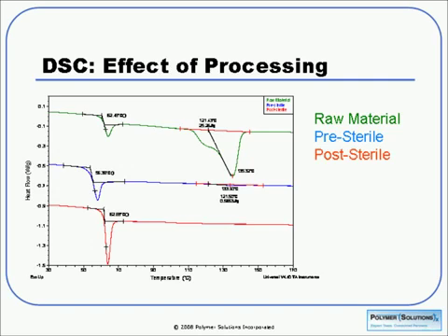We also see an endothermic peak overlaid on our glass transition, and this is related to physical aging. We've mentioned free volume of our samples. Well, if you get up near the TG but not quite to TG, the chains have the opportunity to move around a little bit and get rid of some of that free volume or space between chains, and this is manifested in this kind of a peak. The size of that peak is indicative of how much the sample's aged, and if we went above the TG, that would be erased, and we'd see a step transition only.